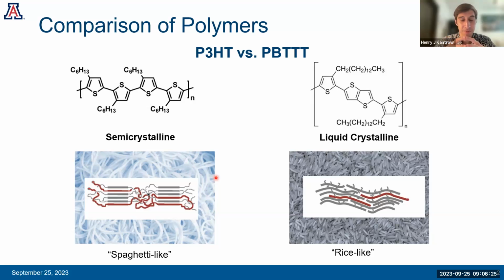Versus in a semi-crystalline flexible chain polymer, where whether you're in a crystal or in the amorphous region, the local environment of your polymer is very different. So we hypothesize that this should vastly increase the degree of static disorder in your flexible chain polymer as opposed to your liquid crystalline-like hairy rod polymer, which we know structurally is more homogeneous.